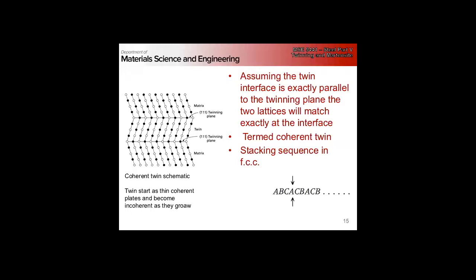What property is going to depend how easy it is to make this fault? Stacking fault energy, right? So right away we know that we're only going to experience this in materials with low stacking fault energy. Aluminum, high stacking fault. Do we ever see twins? Never, right? But austenitic stainless steel, copper alloys, much lower stacking fault, we can easily generate deformation twins, right?